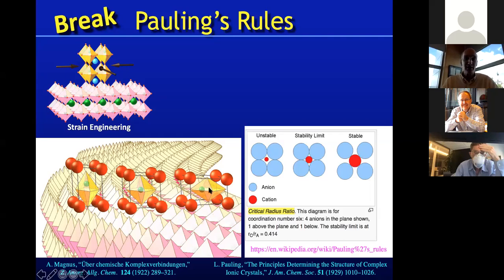That's what I'm showing here in the cartoon form. The green ruthenium wants to get closer to either the oxygens over here on the left-hand side or closer to the oxygens over on the right-hand side, because it no longer can be up against all of them at the same time. The same kind of thing can happen, at least in cartoon form, over here on the left, where I again rain down atoms on top of a substrate that's a little bit too small, and now the coordination polyhedron gets squished in plane, so it gets strained biaxially, but it's stress-free in the out-of-plane direction, so it expands in the out-of-plane direction, and that gives this green cation room to rattle around in the out-of-plane direction, okay?